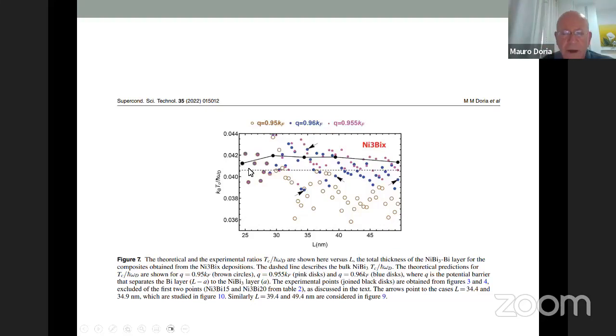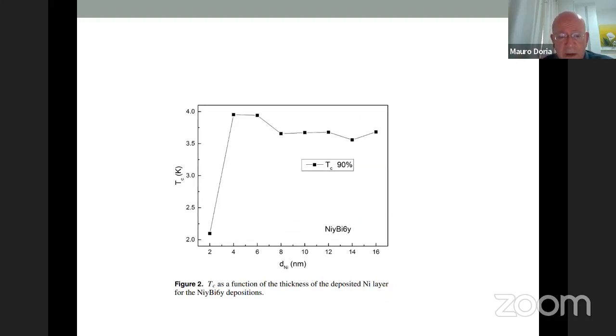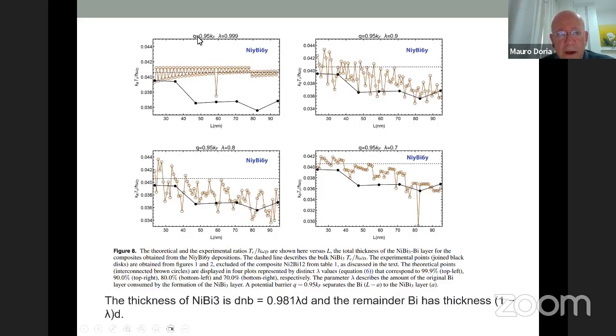The best we could do, and that's why the name of the talk is suggestive, is that the critical temperature is here. The dotted line is the bulk. We see that the oscillations are possible, because this parameter we don't have experimentally; it's a possibility. This is the other system, which is more complicated. According to the height Q of the barrier, and some parameters where we make assumptions on how much bismuth is left over, we see that the oscillations follow the trend of the theory, which are these oscillations here, not the black color, the other color.